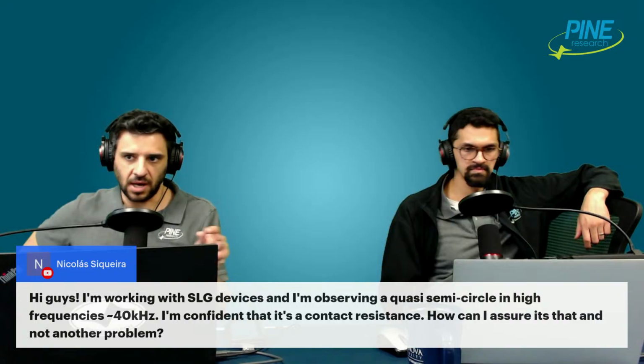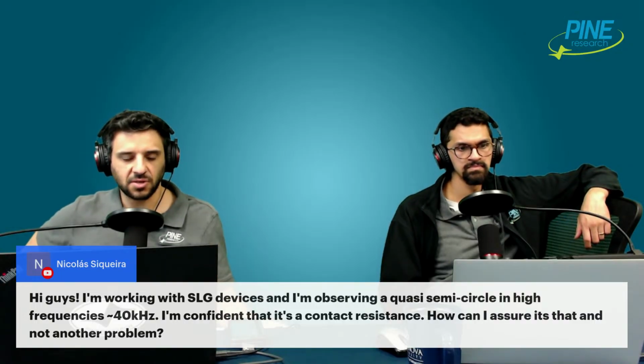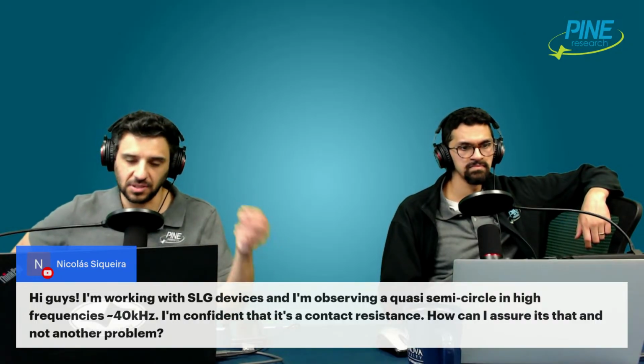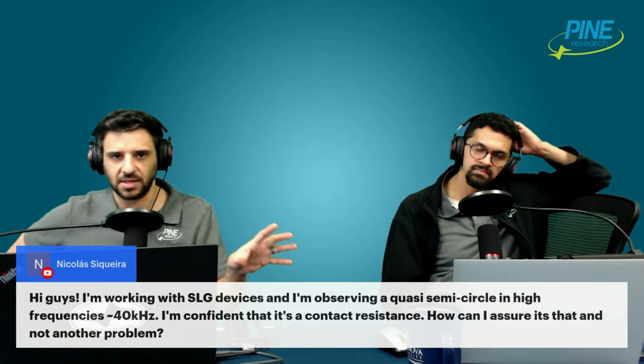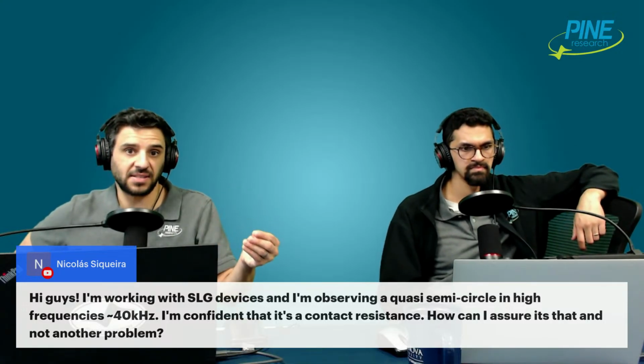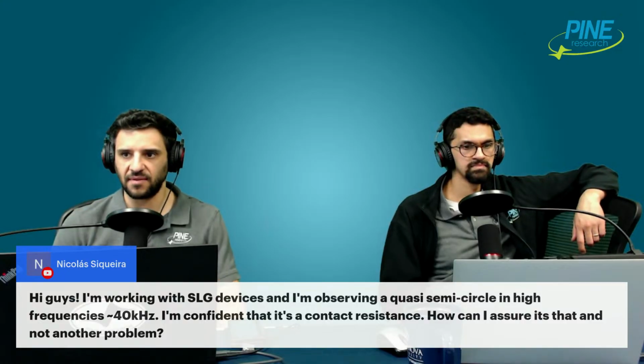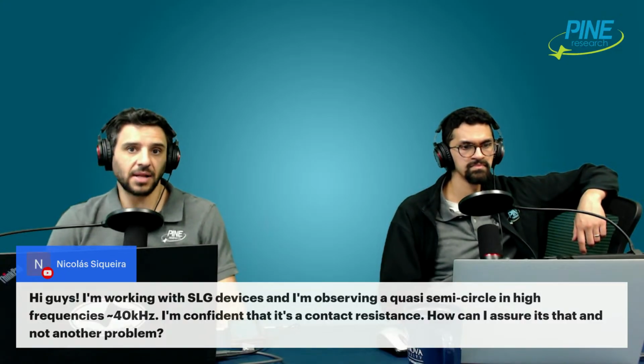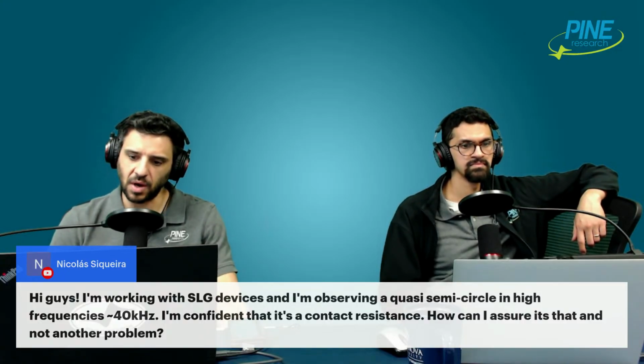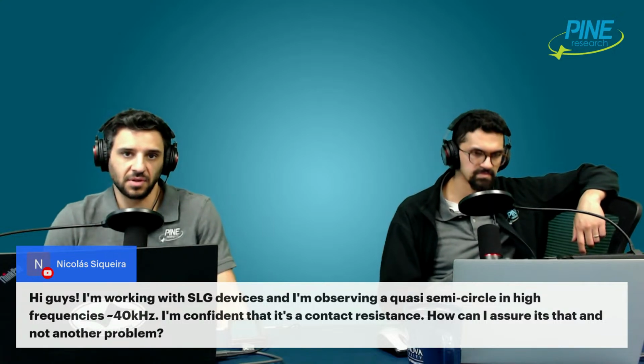contact interface between the substrate and film, because it was very tight, there was no porosity, but that manifested itself. If you just have a measurable enough time constant, it makes a little semicircle, whether it's a quasi-semicircle or a fully formed semicircle.